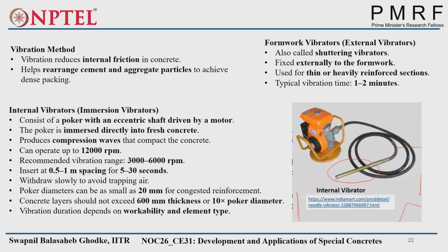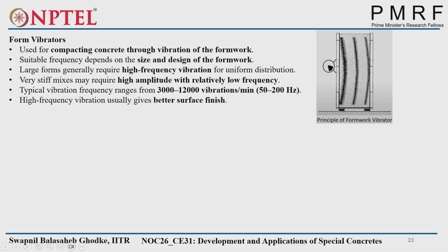Another type of vibrator is the form vibrator. We call it an external vibrator, because we are not immersing it into the concrete. It is also called a shuttering vibrator. Around whatever formwork we have, we can attach the vibrator, vibrate the material and get compaction. Usually we do that for thin and heavily reinforced sections, where we cannot use the poker. Typically the vibration time is 1 to 2 minutes. You see this schematic: suppose this is the external vibrator, this is the formwork, and you attach it here and provide external vibration. The vibration waves are created inside the concrete.